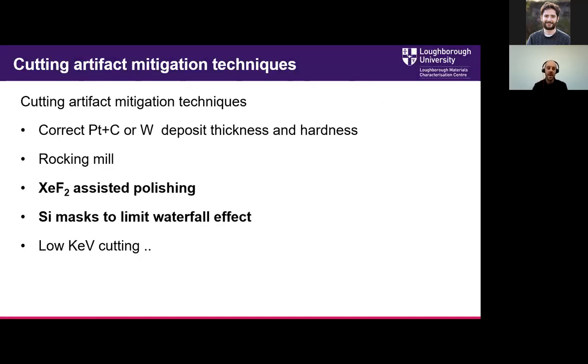So there've been a range of things that we've had to come up with to try and mitigate these issues, and I'll touch on the different ways you can do it in a little more detail. The first and probably the most important thing we can do is select the right platinum, carbon, or tungsten deposit thickness and hardness on top of the sample. This is something traditionally with gallium you don't have to worry about so much. You can just deposit a relatively fine layer of platinum and make a cross section. But with the PFIBs, you have to think about what voltage or what carbon percentage you use for that platinum capping layer. People have also come up with rocking milling.